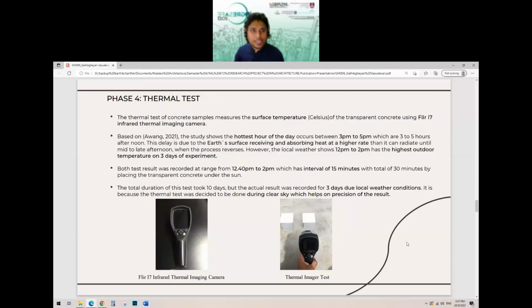For phase 4, the thermal test of the concrete sample measured the surface temperature in Celsius using an infrared thermal imaging camera. Based on previous studies, the hottest hour of the day occurs between 3 to 5 p.m. However, the local weather at the time of the experiment showed 12 p.m. to 2 p.m. had the highest outdoor temperature on the 3 days of experiment. So all the tests were recorded from 12:40 p.m. to 2 p.m. at an interval of 15 minutes, for a total of 30 minutes, by placing the transparent concrete under the sun.